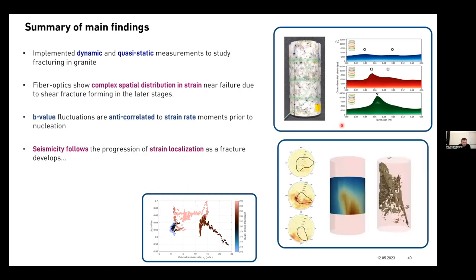We found that the seismicity does follow in the latter stages the localization and the progressive localization of the fracture as it develops. And this was confirmed with XRCT, fiber optics, and acoustic emissions. So that's a nice finding in terms of that the seismicity in the latter stages is representative of a region of rock that is deforming in a fast rate and highly localized manner. So this is possibly something to test at the next scale up.